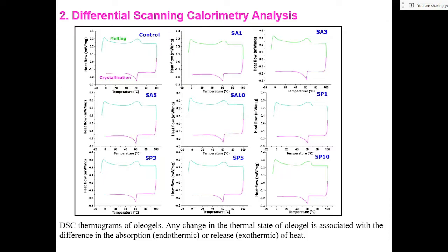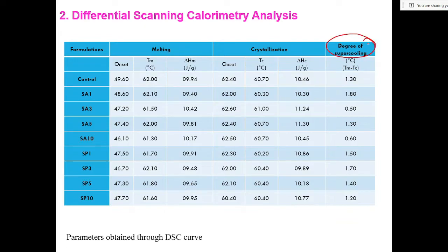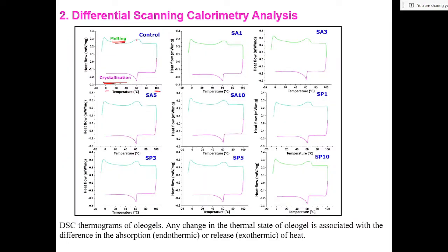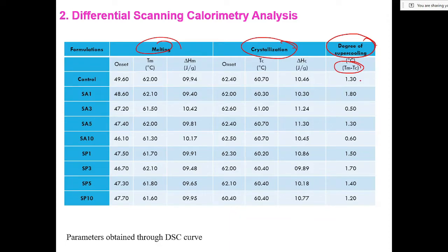Okay, and the first one is the melting curve, second one is the crystallization curve. So we did the analysis in the range of 0 to 100 and back. We got melting peaks and crystallization peaks at different temperatures depending upon the nature, and then we had this degree of supercooling, which is basically the melting temperature minus the crystallization temperature. There will always be a difference between the melting temperature and the crystallization temperature. That difference is regarded as the degree of supercooling, and it affects the crystallization process. So over here if you see, it was 1.30 degree centigrade in the control, and in the samples it has varied in a composition dependent manner.